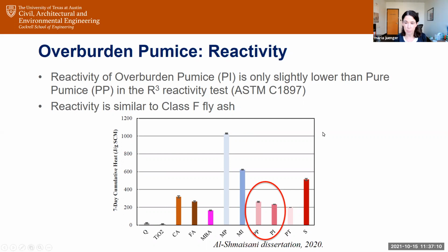This particular test is a reactivity test that's now standardized in ASTM C1897, and we call it the R3 test. In this particular plot, I'm going to show you this plot a few times with different circles on it, looking at different materials. If we look at something that's inert, like a quartz or titanium dioxide, this value here is low. If we look at something like a fly ash here, this value is medium. If we look at a pumice, the pure pumice, the PP, or the impure pumice, this overburdened pumice, the PI, their reactivity in this particular test method is about the same as fly ash. So they both actually meet our goal of being just as good as fly ash. And yet the impure one is a waste product, just like fly ash as well.